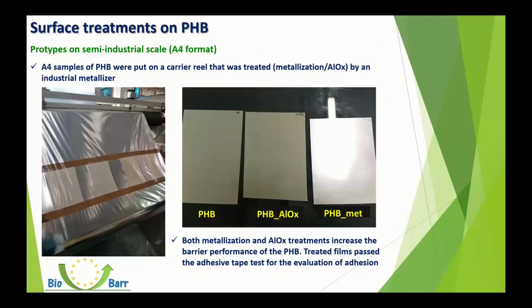So we realized some prototypes on semi-industrial scale of metallized and AlOx-treated PHB samples. We realized A4 samples putting untreated PHB on a carrier reel that was treated by an industrial metallizer in order to obtain metallized film and AlOx-treated film. Both metallization and AlOx treatment, as I discussed previously in the other presentation, are able to improve barrier performances of the PHB. And also, this treatment passed the adhesive tape test for the evaluation of the adhesion.